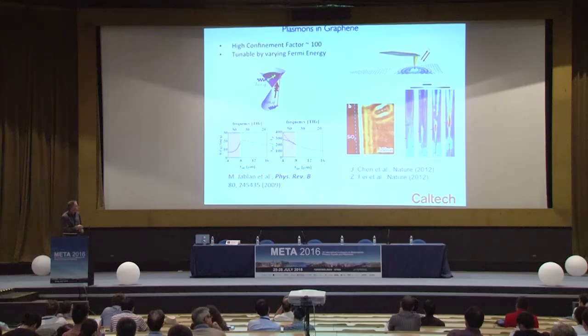But of course, to change the complex permittivity of materials, we need to go to lower carrier densities, where by applying an electrostatic potential, we can change the carrier density by a much larger fraction than the few percent that we're able to achieve in metals. And of course, that leads us to consider the possibility of changes in the permittivity of graphene.